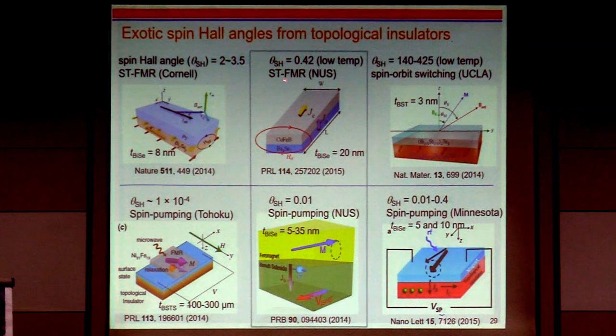So we tried to use the same technique, ST-FMR. Then we found the spin Hall angle now improved suddenly 42 times, to 0.42, only at low temperature. But anyhow, the field is really messy. If you look at the Tohoku report at about the same time, their spin Hall angle is 0.0001. Okay? And if you look at the UCLA report, the spin Hall angle is up to 425. Of course, slightly different materials. This is BSTS, this is antimony doped. But no matter what, how can the behavior change 7 orders of magnitude from here to here?